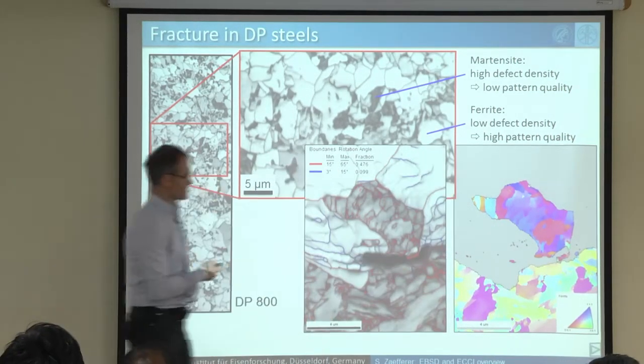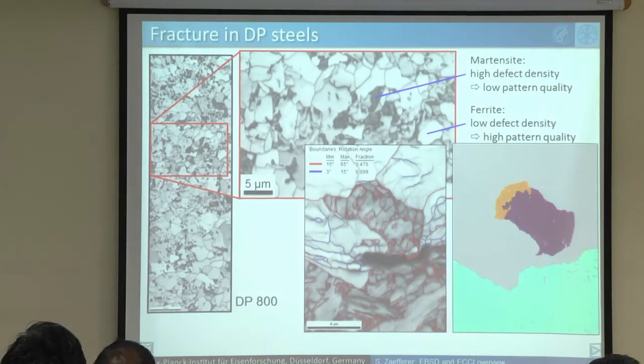And we reconstructed using the software where the austenite is, and we found that the crack here is always in between, separating two different original austenite grains. Always. We never find a different case. It's never going right through an austenite grain. It always cracks along a grain boundary of two original austenite grains which were there at high temperature, which you don't see any longer here.